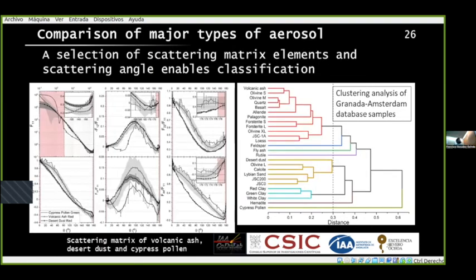And this is the other aspect of aerosol measurements. We can measure the scattering matrices of mineral dust, and we can measure also the scattering matrices of pollen. We just go and collect pollen from a tree and measure it through the aerosol generator. And then you see that the curves are very different. For example, the polarization curve of cypress pollen is very different from the one from mineral dust. Still, mineral dust has some differences. So in this case, Saharan dust and volcanic ashes are very different in this element. So the summary of this is you can measure three scattering matrix elements at three different angles.